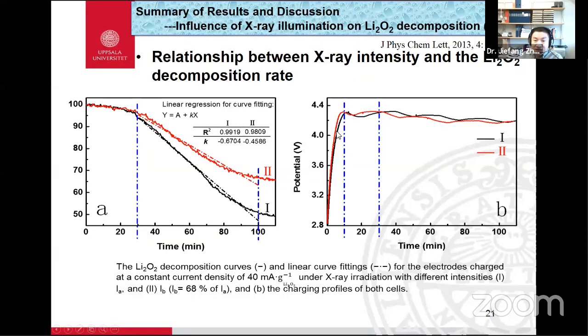But the electrochemical profile doesn't change too much. This is understandable because the X-ray only hits a very small spot on the battery, less than 1 millimeter in diameter, so it will not change the electrochemical profile of the whole battery too much.